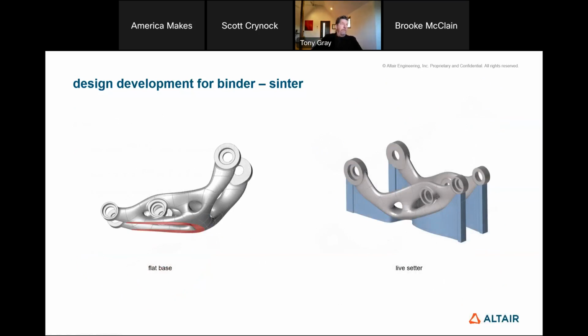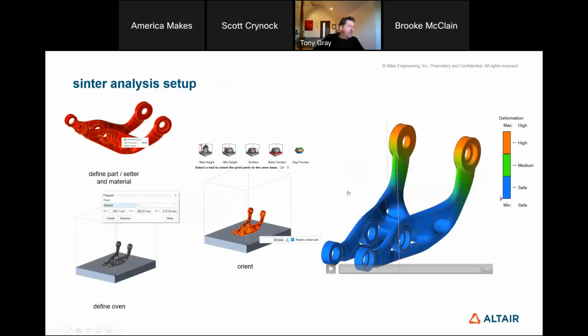So with binder sinter, sometimes you can print on a flat base, so it's a fully self-supporting part like this, or you create live setters, so you actually print a part that your part of interest sits on, and then it shrinks at the same time. The shrinkage is on the order of 20% during the sintering process. So these are the two strategic approaches. For this presentation, I've just shown the potential of the one not on a setter, but again, this is the print 3D process for binder sinter.